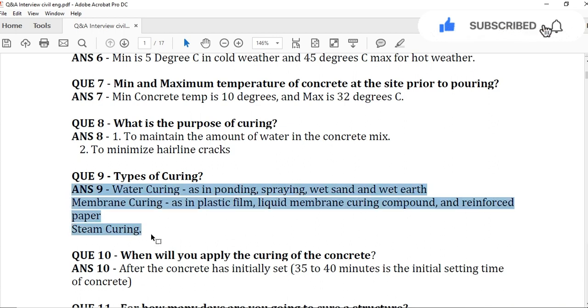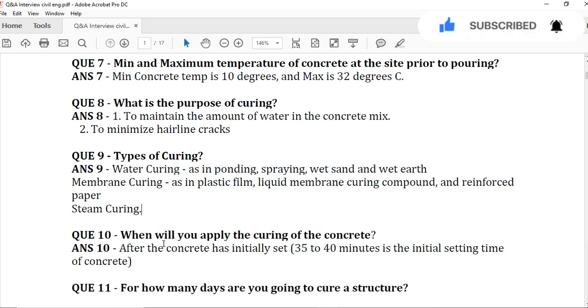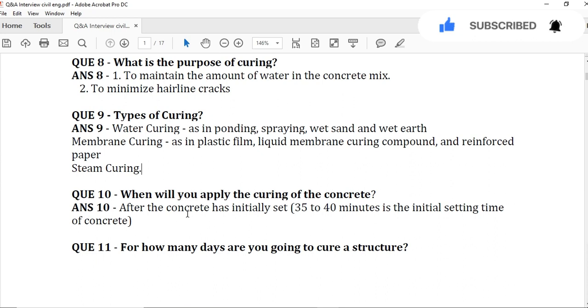Question number 10: When will you apply the curing of the concrete? After the concrete has initially set, 35 to 40 minutes is the initial setting time of concrete. But as per site condition, like practically, minimum you can start curing after 24 hours. But it depends on the weather condition.